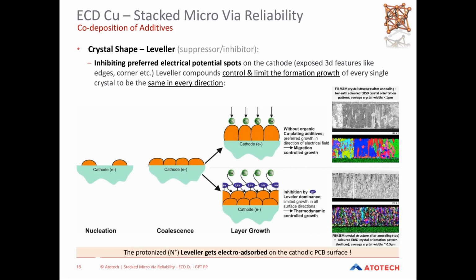You will create quite uncontrolled rough copper plating. Therefore, usually the leveler is required to control the crystal shape, to have a uniform nucleation and crystallization. And by the leveler, you will create very uniform shaped and, in this example, very small crystals. The leveler itself is attracted by the electrical field on the surface, and this lets it adsorb on the surface, but normally the leveler will not get co-deposited into the bulk of the copper plating process. It will always grow with the surface and will stay adsorbed on surfaces.